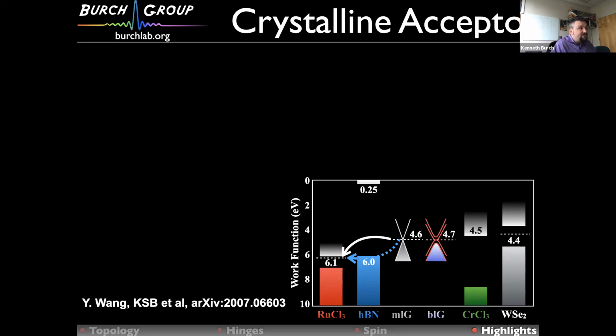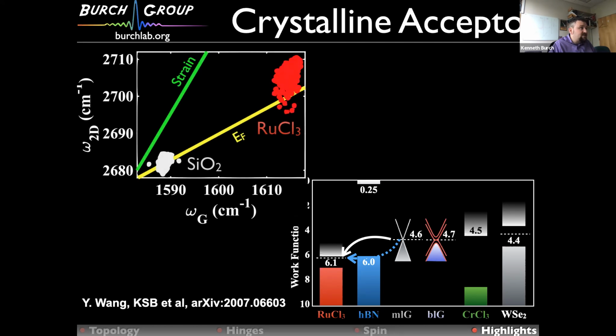There is something special, however, about ruthenium. So if you look at chrome chloride, which basically has the same physical structure, it's just a charge transfer insulator, and so actually its conduction band is far, far away, and there is no chance of getting charge transfer from graphene into chrome chloride.